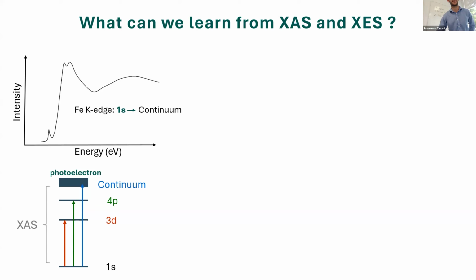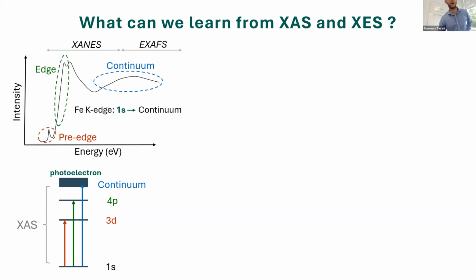And you see all these little bumps, these features, at least a spectroscopist would call them features, in the signal. These are due to the scattering of the ejected electron with the vicinity of the atoms surrounding the given photo-absorbing element. It boils down to this: these features are extremely sensitive to the local structural environment. Sorry, let me just add this. This would be a breakdown of a typical XAS spectrum.